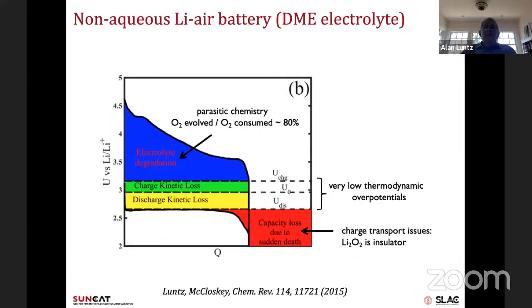drive it up, try to charge it, and this is a charging, and these are all done at constant current, the potential just keeps going up, up, up. And that's due to the fact that you have a lot of parasitic chemistry going on. Something is reacting with the electrolyte and depositing lithium carbonate on the electrode. And so you just passivate it again. I won't try to go into too much of this.